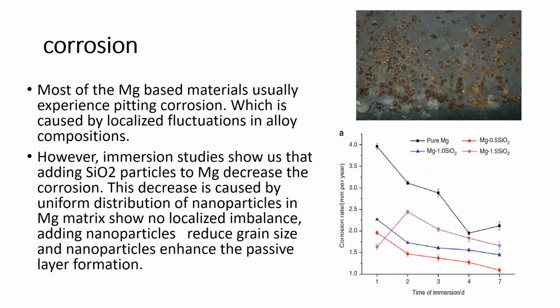Most magnesium-based materials usually experience pitting corrosion, which is caused by localized fluctuations in the alloy composition. However, immersion studies show us that adding silicon dioxide particles to magnesium decreases the corrosion because of the uniform distribution of nanoparticles, and nanoparticles enhance the passive layer formation. As we can see, magnesium with 0.5% volume silicon dioxide has the best corrosion rate.